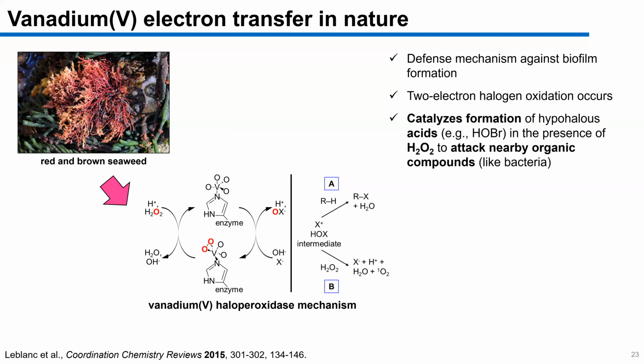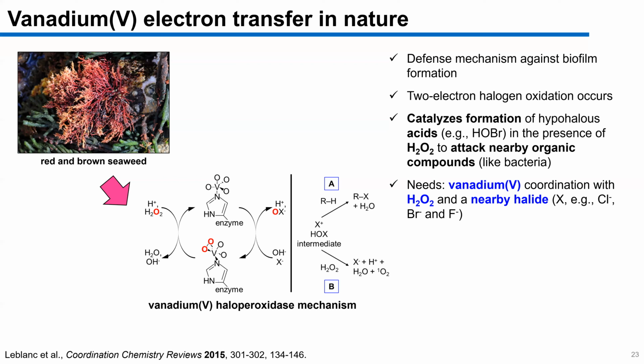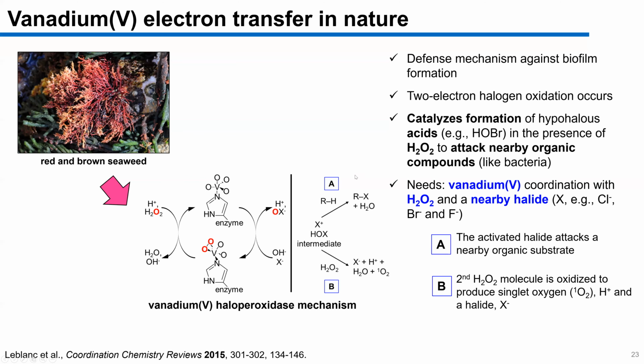The formation of this acid and other reactive species are able to attack nearby compounds like bacteria to prevent biofilm formation. What you need for this enzyme to activate is a vanadium 5 coordination in your center or cofactor. You need the hydrogen peroxide and you need a nearby halide in order for this to work. So the activated halide, once the enzyme is active, is able to become oxidized to form the hypohalous acid and attack the nearby organic substrate. That's this A pathway here. And in the B pathway, you can also get incorporation of a second hydrogen peroxide molecule to form singlet oxygen, protons, and release a halide, X minus.